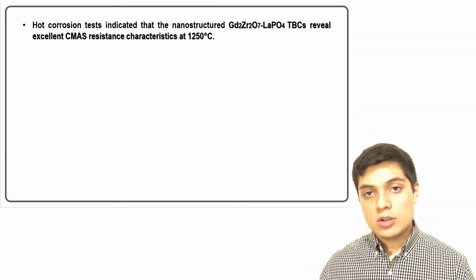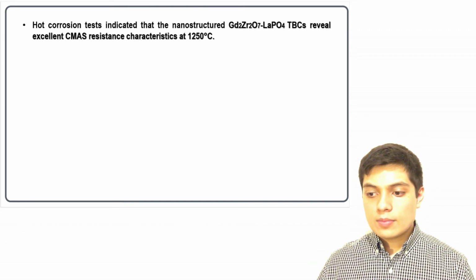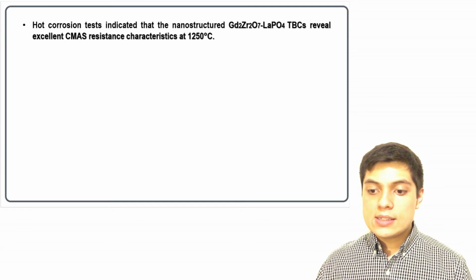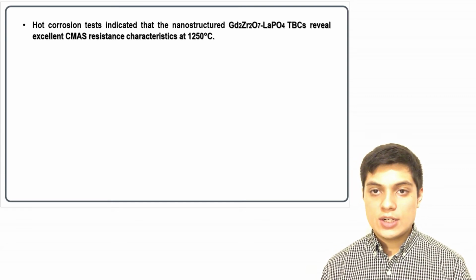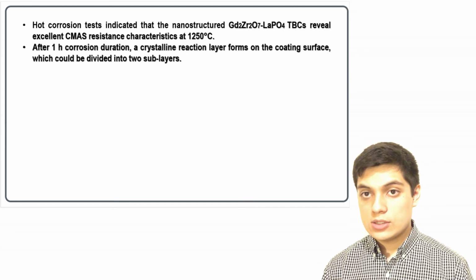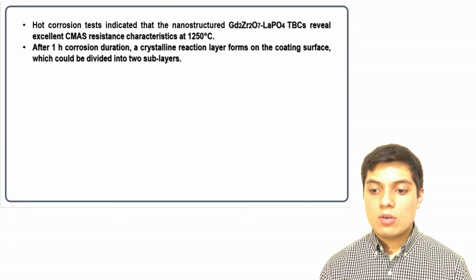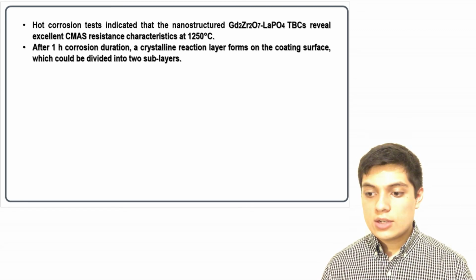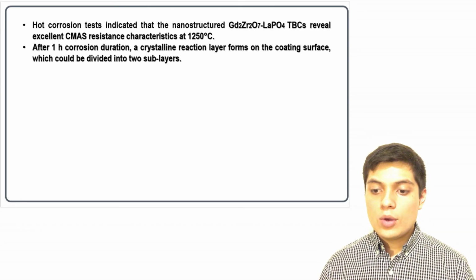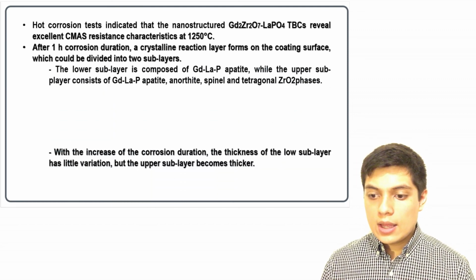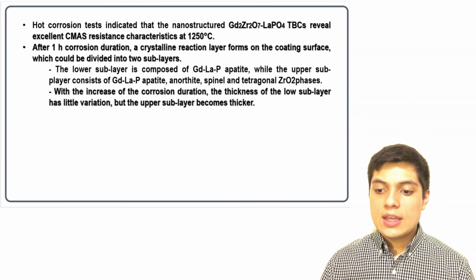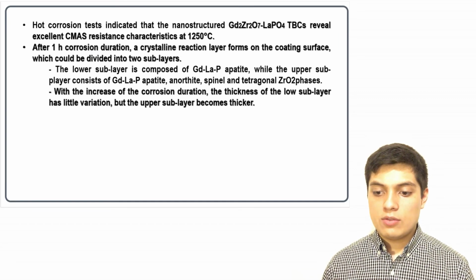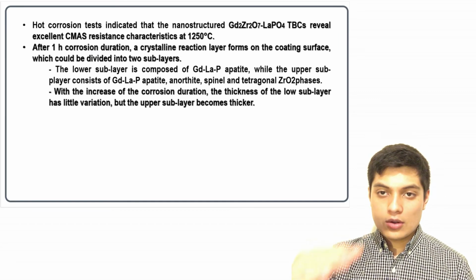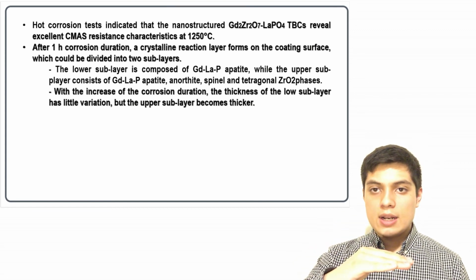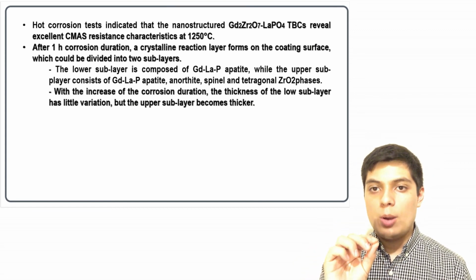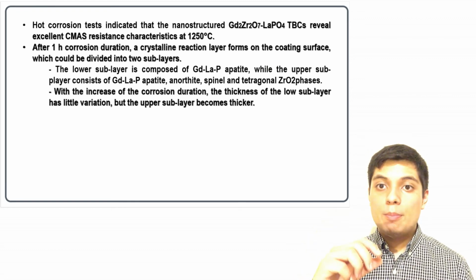The gadolinium zirconium oxide lanthanum phosphate as a thermal barrier coating reveals excellent CMAS resistant characteristics at 1250 Celsius degrees, and after 1 hour of corrosion duration, a crystalline reaction layer forms on the coating surface, which could be divided into two sublayers. With the increase of the corrosion duration, the thickness of the lower sublayer has little variation. So this means that the lower layer has a minimum of variation of thickness, but the upper sublayer becomes thicker.